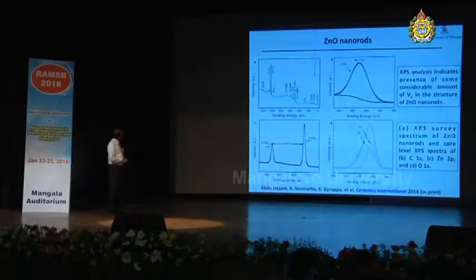And these zinc oxide nanorods have been subjected to the XPS analysis, and this is the entire spectrum. And you have the carbon here, the adsorbed carbon from the atmosphere, and the zinc peaks and the oxygen peaks.